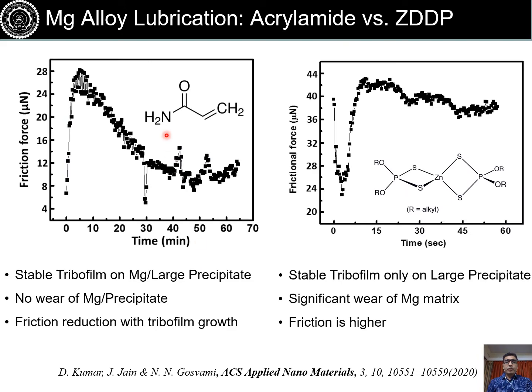So in comparison to ZDDP, acrylamide shows just the opposite behavior, where friction increases and then drops, whereas in the case of ZDDP, friction first drops on the precipitate, then increases, and then starts to hover around some values. But of course, with ZDDP this behavior is not seen on the matrix or fine precipitate region, whereas acrylamide shows this behavior on the matrix as well as on the large precipitates, which makes it a very important additive for magnesium based alloys. And AFM allows us to systematically study these differences between two different types of additives in very localized regions.